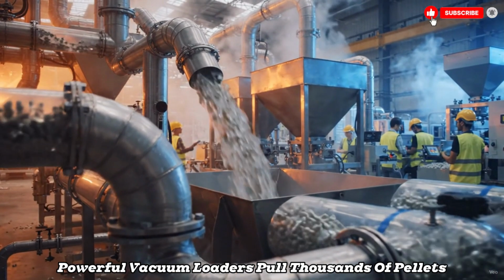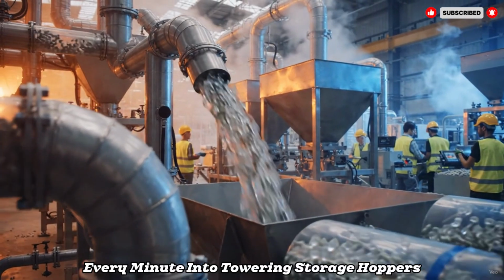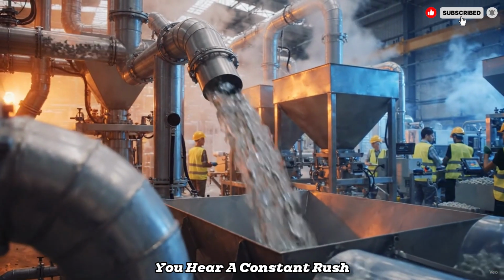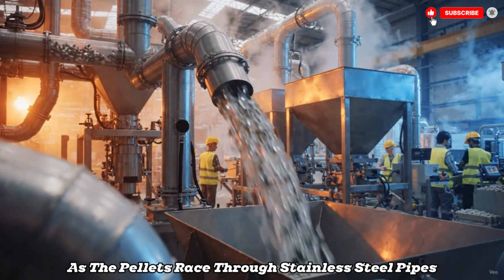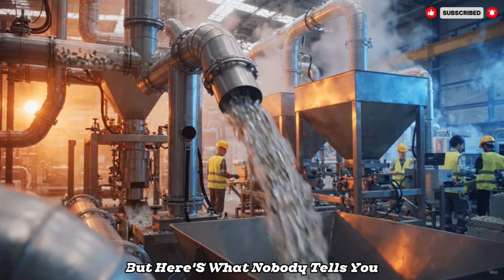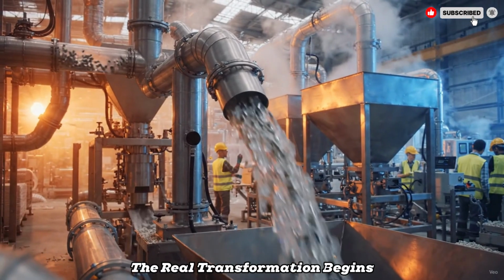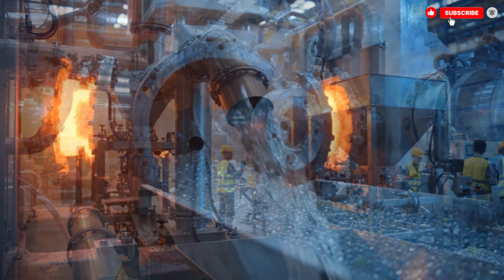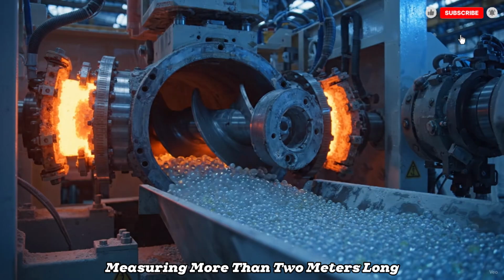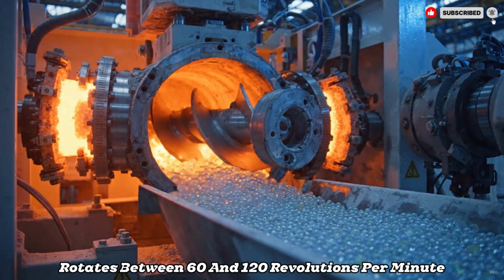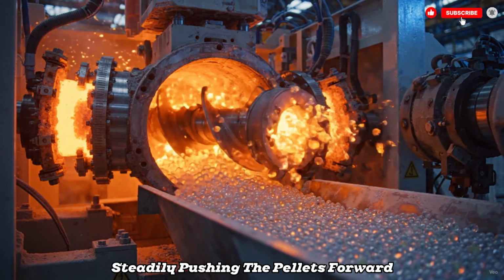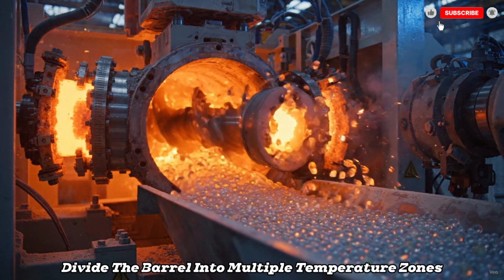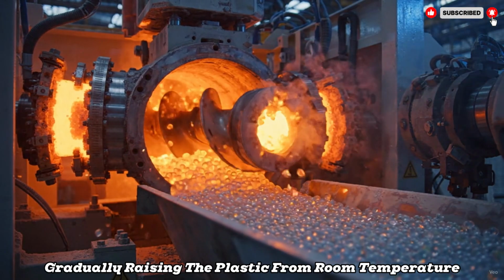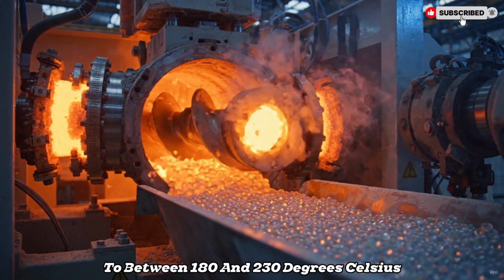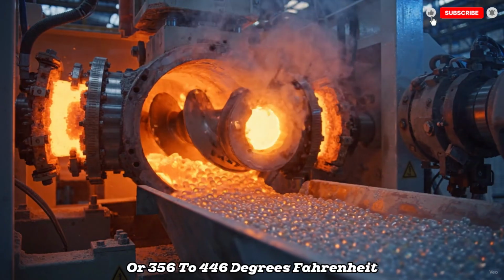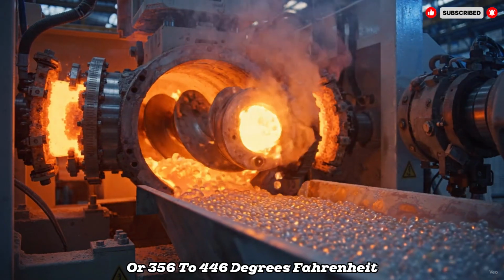Powerful vacuum loaders pull thousands of pellets every minute into towering storage hoppers positioned above the extrusion machine. You hear a constant rush that sounds like a powerful windstorm as the pellets race through stainless steel pipes. But here's what nobody tells you. The real transformation begins the instant those tiny pellets meet intense heat. Inside the extruder, a massive steel screw measuring more than 2 meters long rotates between 60 and 120 revolutions per minute, steadily pushing the pellets forward. Electric heaters divide the barrel into multiple temperature zones, gradually raising the plastic from room temperature to between 180 and 230 degrees Celsius, or 356 to 446 degrees Fahrenheit.